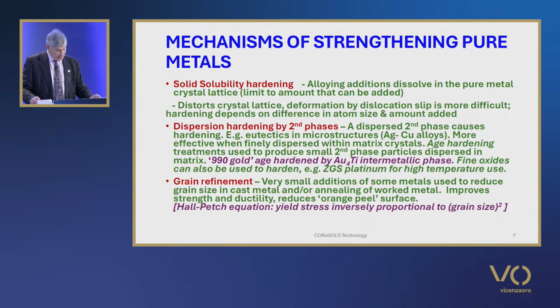Solid solubility hardening. In hardening by solid solubility, alloying additions dissolve in the pure metal. That is, they are incorporated into the crystal lattice of the pure metal, and this results in the distortion of the crystal lattice, making dislocation slip more difficult. That means it requires more force to deform the metal.